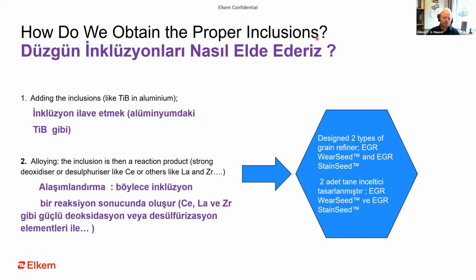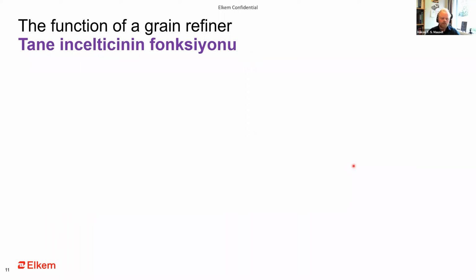So how do we obtain the proper inclusions to get grain refining? Well, we could do like you do in aluminium by adding the specific inclusions you need, for example, titanium borides in aluminium. Or we can choose another way, and that is what we have done in Elkem. We do it by alloying. So the actual inclusion is a reaction product from the alloy that we put into the steel. So typically it is a strong deoxidizer or desulfurizer like cerium or lanthanum, zirconium, and other reactive elements that you can put into steel. And by using this principle, we have designed two types of grain refiners. We have the EGR Wear Seed and the EGR Stain Seed. And then we will come back to them.